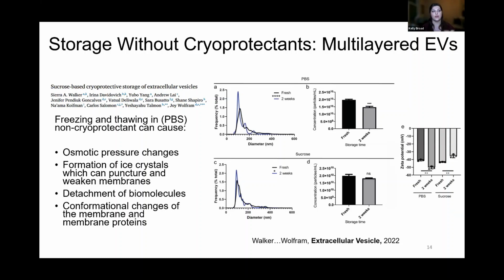And the freeze-thaw cycle in a non-cryoprotectant can cause osmotic pressure changes, the formation of ice crystals, which can puncture and weaken membranes, the detachment of biomolecules of interest, and conformational changes to the membrane and membrane proteins. As such, we wanted to investigate whether storage without cryoprotectants was potentially creating these artifacts.